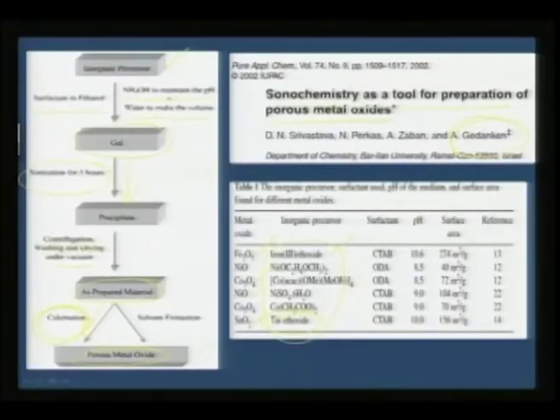So that is the beauty, because most of the wet chemical routes involve isolation of a metal oxide and then converting it into a crystalline phase by another protocol involving calcination for long hours or for short time. But what we see from the sonochemical approach is you do not even need to calcinate the compound. Directly by bubbling it, because of the cavitation and the high temperature that you can generate locally, these compounds are not only amorphous in the beginning, but they tend to crystallize as you sonicate it for a few hours.